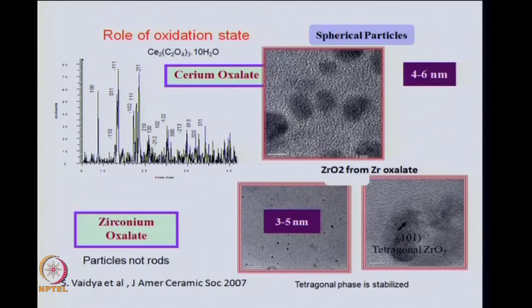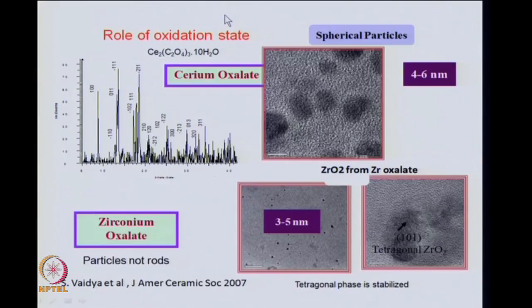Now, we also see that the role of oxidation state plays a part, because whatever metal oxalate rods we discussed, in those we always had the metal in the divalent oxidation state, like cobalt 2+, nickel 2+ reacting with oxalate ion in the microemulsions gives you rods with CTAB as a surfactant, a cationic surfactant. However, if you choose the same system, CTAB based cationic surfactant, and study the synthesis of cerium oxalate or zirconium oxalate, we get particles and not rods, although we are using CTAB as a surfactant. So, it suggests that the oxidation state is important, because cerium here is not divalent, it is trivalent, and zirconium here is tetravalent and not divalent.